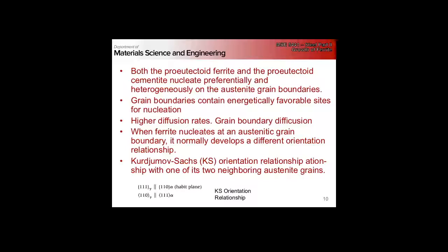And that the proeutectoid ferrite nucleates heterogeneously at the austenite grain boundaries, and typically the ferrite nucleates with a preferential orientation relationship with one of the austenite grains. It forms this Kurdjumov-Sachs orientation relationship.